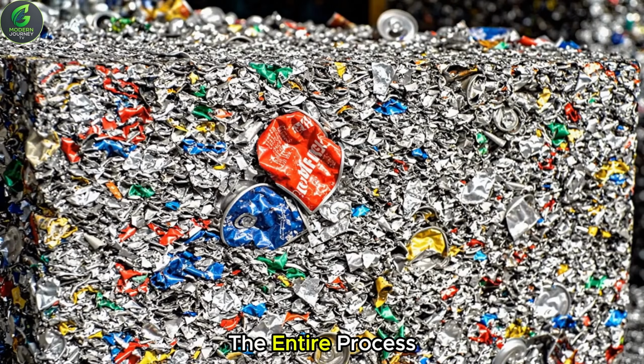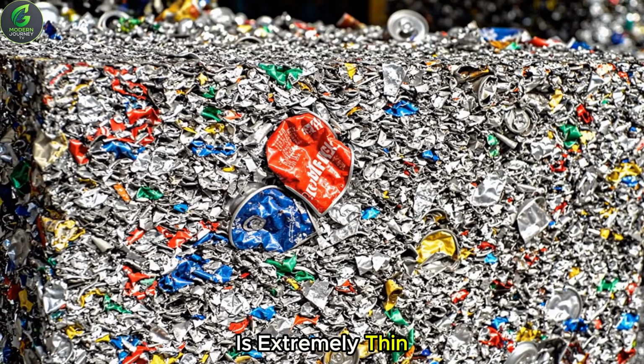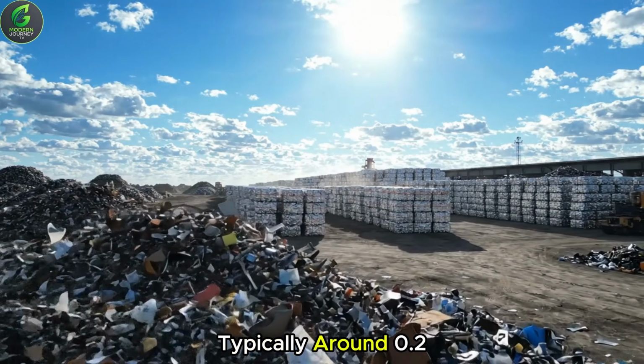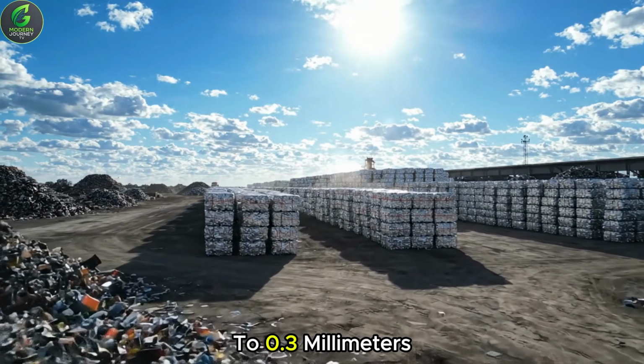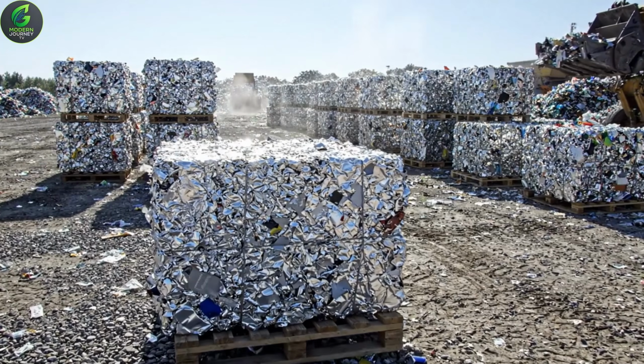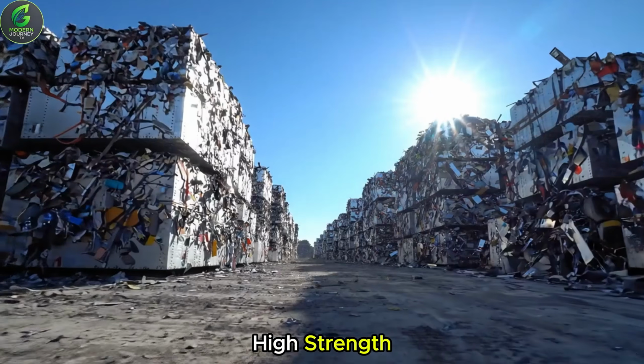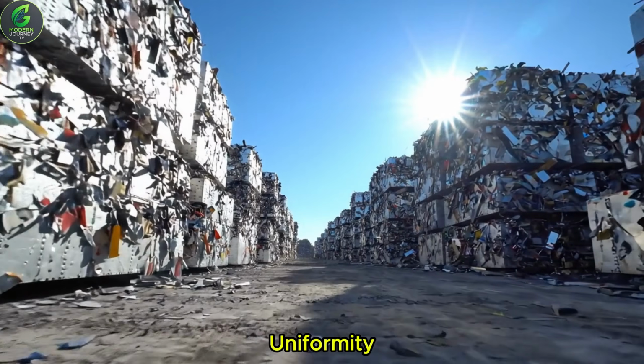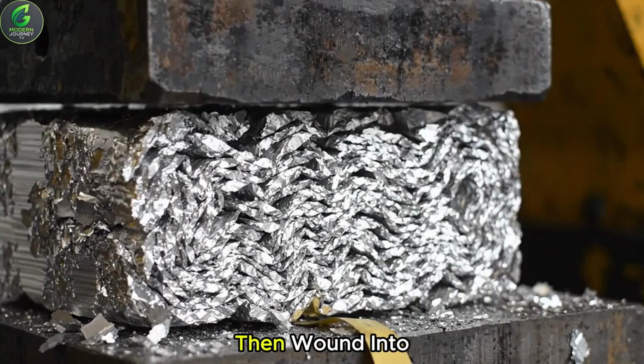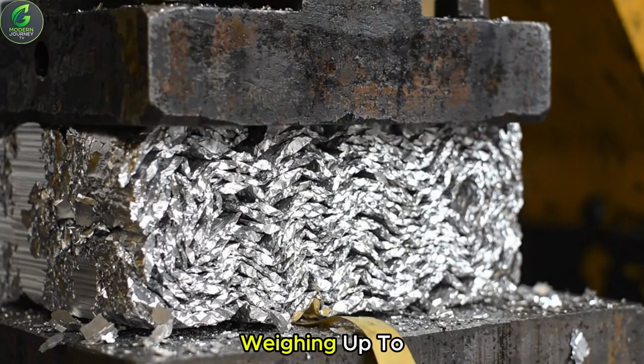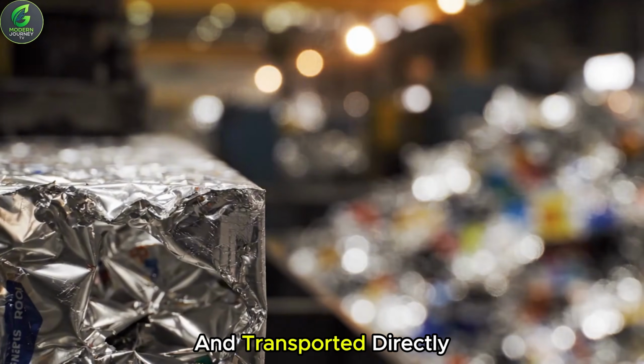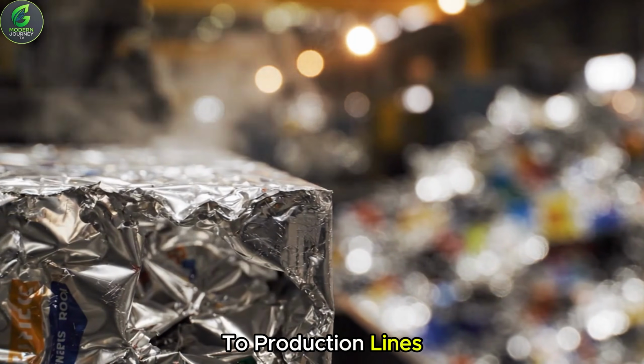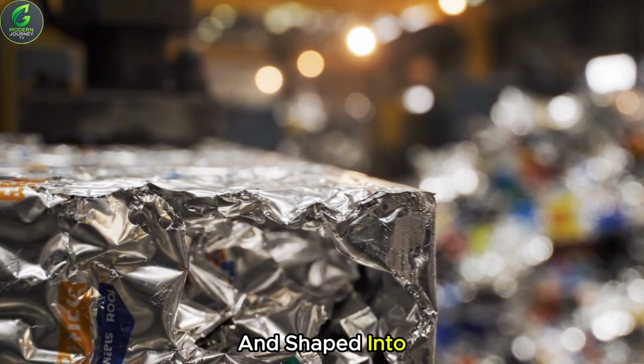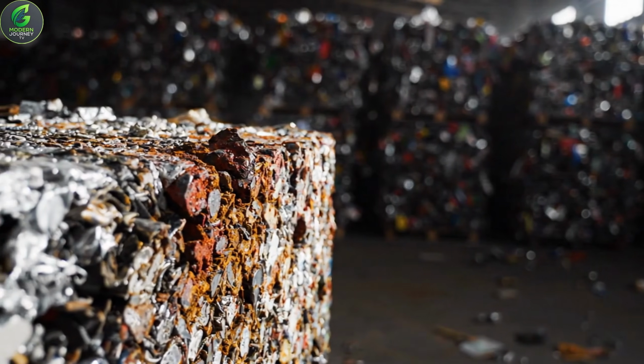The result of the entire process is extremely thin aluminum sheets, typically around 0.2 to 0.3 millimeters thick for beverage cans, while still maintaining high strength, pressure resistance, and uniformity. These sheets are then wound into large coils, weighing up to tens of tons, and transported directly to production lines, where they will be stamped and shaped into finished cans.